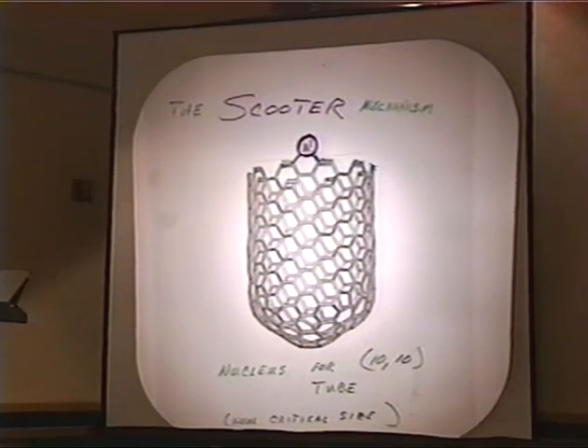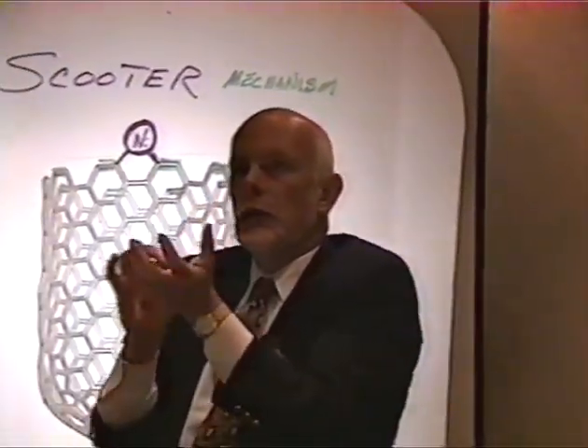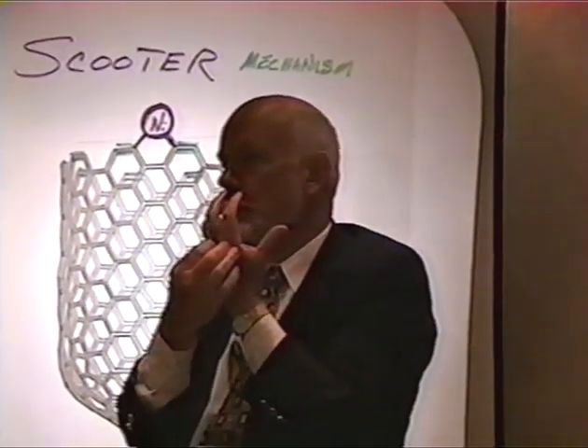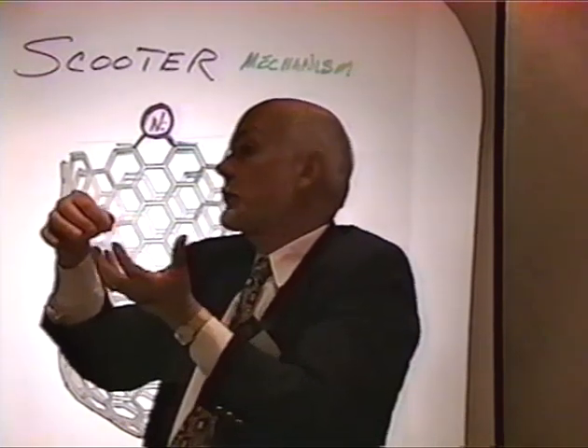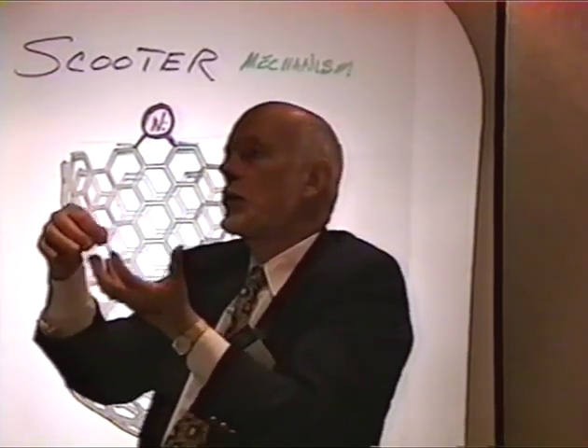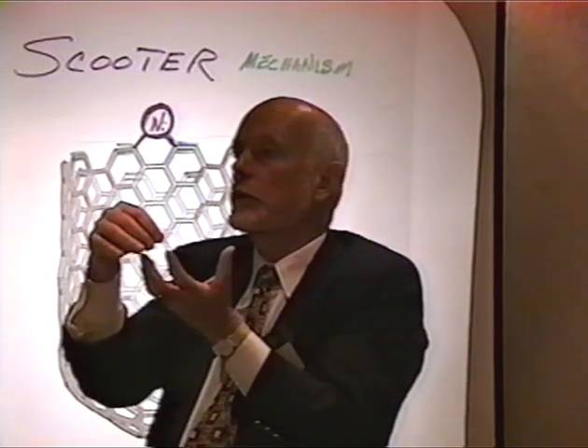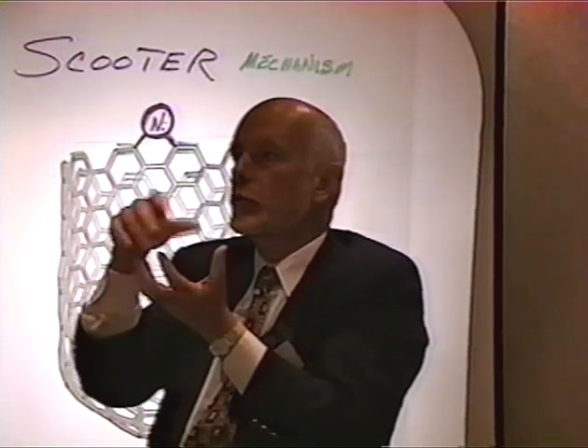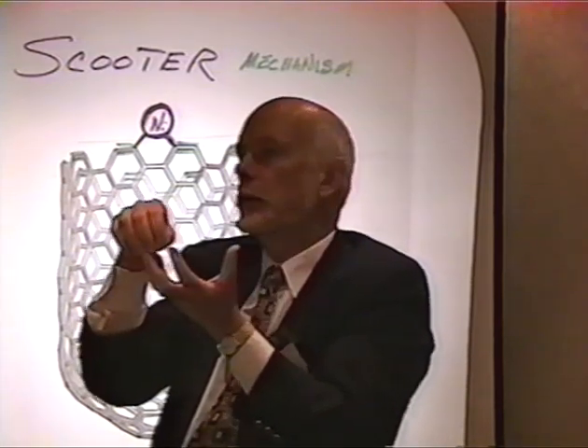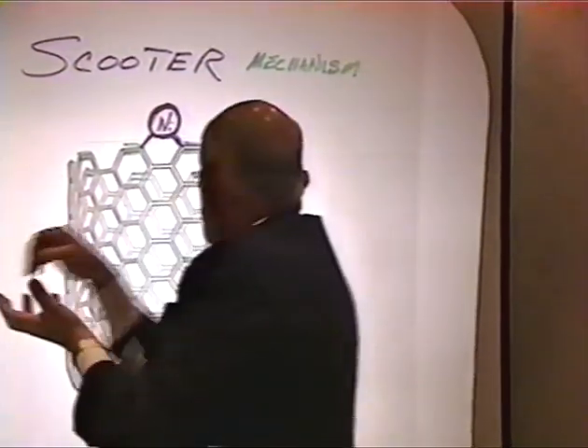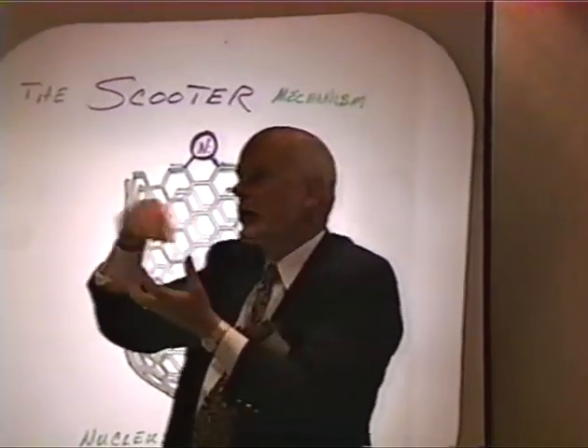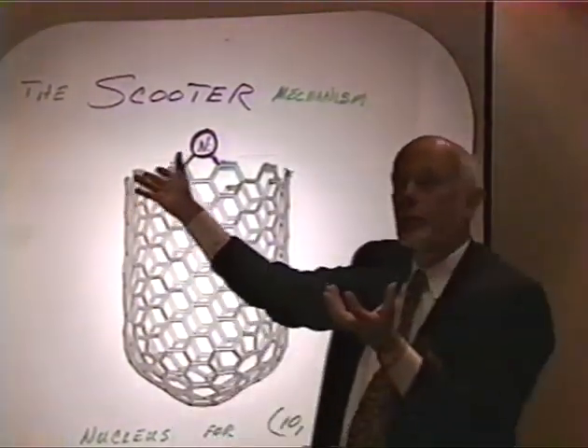And this thing starts growing and starts curving and rearranging to drop its edge energy, but now there's some metal atoms, nickel or cobalt, condensing in the carbon vapor. And if one or two of these hit the side of it, move around, it's certainly going to bind on that open edge much more strongly than on the surface. And what will that do? Well, we know that nickel and cobalt and iron and these other atoms are extremely good at catalyzing the rearrangement of carbon networks, particularly aromatic carbon. And that's all we think this little metal atom does. It goes scooting around. It doesn't have to be just one, but one is probably enough in many cases.